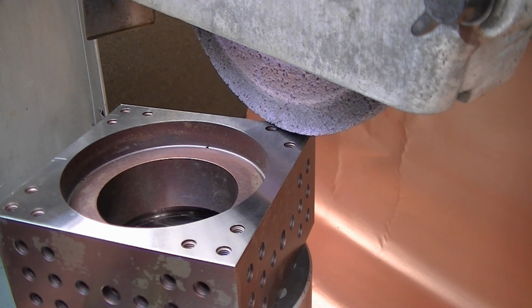The other thing is how you dress the wheel and how much the wheel has been used, or how much the wheel has worn and how dull it is. A lot of people use coarse wheels and dress them fine, and that automatically creates a situation where the pressure it takes to initiate a cut on the wheel is higher than if the wheel was dressed for what it's designed for, meaning dress it to cut with the grit size that it is. Don't try to dress it fine and get a shiny finish. The shinier it gets, typically means the more that wheel's burnishing instead of cutting freely. So there's a trade-off there.